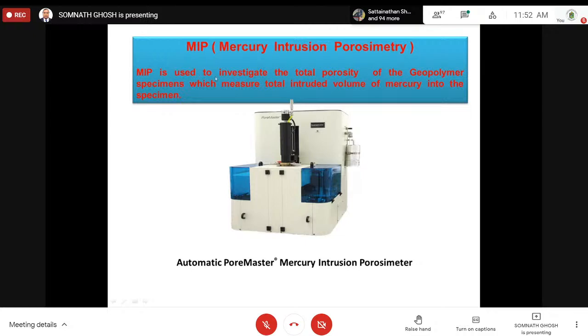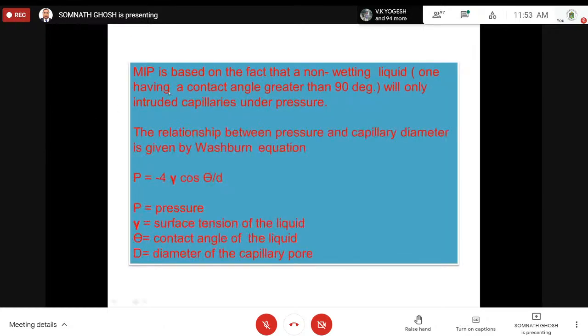So, MIP is used to investigate total porosity of geopolymer or alkali slag, which measures the total intruded volume of mercury into the specimen. What they do, they try to intrude mercury by putting high pressure. And the mercury is going inside. They are measuring how much mercury is going inside, volume of mercury. And from there, they are trying to predict the pore volume, maximum pore diameter, etc. So, this is the kind of thing.